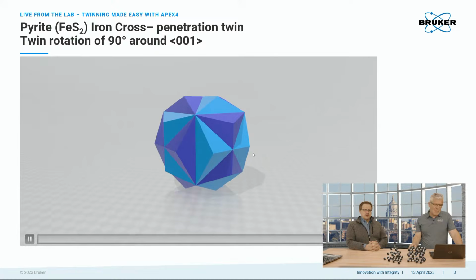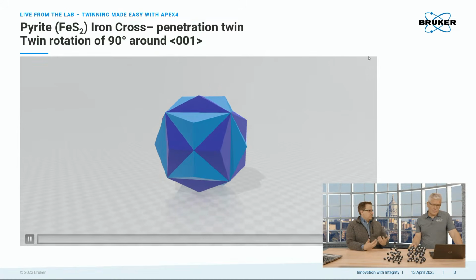It's very pretty. Now, do these form to minimize the amount of energy in the system? It's interesting, and I think that's still discussed. You could argue we have additional symmetry, so it should have lower energy, but that's typically not the case. In the case of these contact twins, there's actually energy involved on the plane, and it's typically described as energy per area. Often there's a kinetic reason why they might form. But thermodynamically, the twin always has higher energy than the crystal itself.